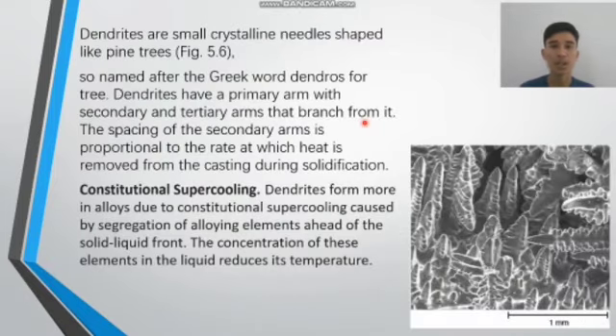Dendrites are small crystalline needles shaped like pine trees, picture 5.6. So named after the Greek word dendros for tree. Dendrites have a primary arm with secondary and tertiary arms that branch from it. The spacing of the secondary arms is proportional to the rate at which heat is removed from the casting during solidification. Constitutional undercooling. Dendrites form more in alloys due to constitutional undercooling caused by segregation of alloying elements ahead of the solid-liquid front. The concentration of these elements in the liquid reduces its temperature. Next,